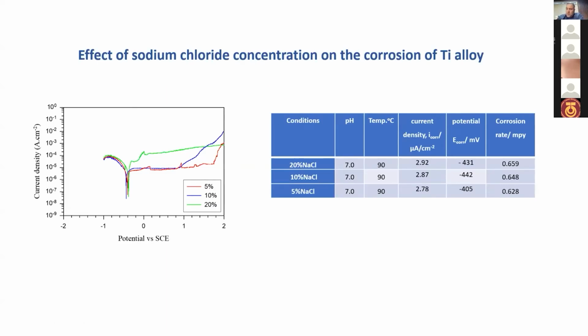Now, for the titanium, here we note that there is no significant effect on the corrosion behavior of the titanium after this test. So we note that there is a slight increase in the corrosion current density and corrosion rate. The corrosion current density increased from 2.7 to 2.9 microampere per centimeter square, and the corrosion rate increased from 0.6 to 0.65 mils per year when the chloride concentration increased from 5 to 20.